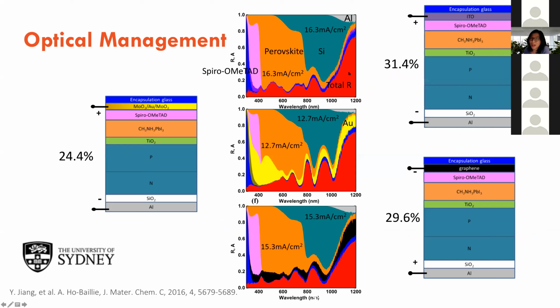So what we do is we simulate different kinds of tandem cell structure to see what happens. There are 3 different cell designs in this case. You have the silicon cell on the bottom, and then the perovskite, where the titanium dioxide is the electron transport layer, and you have the spiro-OMeTAD, which has a really, really long chemical name, so we call it spiro for the hole transport layer. All 3 cells have similar perovskite and silicon cell structure, except the very top, which is the transparent conductive layer. It's either a stack of very, very thin gold that lets light in and also conducts electricity, or ITO on this side, or graphene, which conducts electricity, and if you have it thin enough, it will let light through. So what we do is we just run some optical simulation to see what happens.